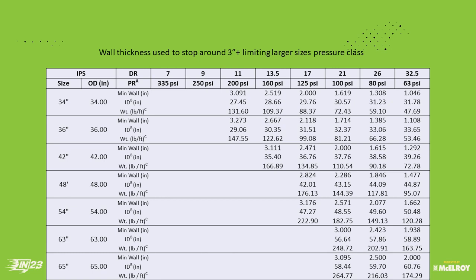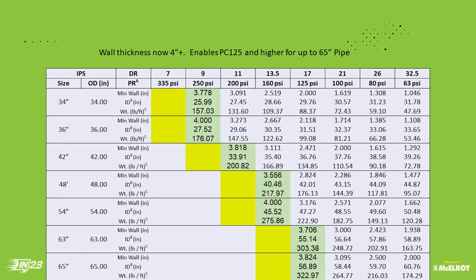Now we've moved to the next level — 4-inch wall thickness is not uncommon and shows up on many common data sheets. That brings a whole other pressure class into performance that we didn't have before. Now you're getting into 54-inch DR13.5 with a pressure class of 160 PSI. That opens up a lot of windows into markets Mike was talking about — traditionally steel, HOBAS, concrete — that nobody even considered polyethylene for in the past. That's why we're finally seeing more large-diameter jobs going to polyethylene. The yellow on the chart is the next step — getting up to 5-inch wall thicknesses, which can reach pressure classes you couldn't do before and opens a whole other range of possibilities.